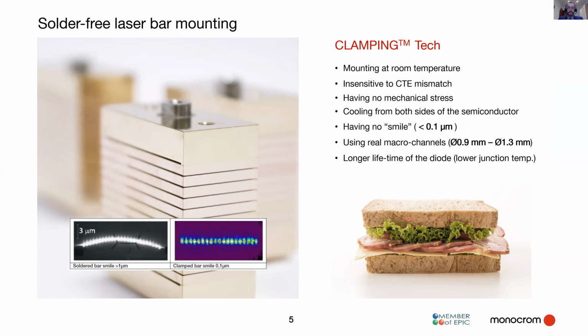Our mounting technology for laser bars is somewhat different compared to what's common on the market. At Monocrom, we make sandwich structures comprising 2 electrodes, which is shown on the lower right section of the slide. In between the electrodes lies the semiconductor. We clamp this structure, and while applying a force, we ensure good mechanical and electrical connection to the laser bar. And we avoid using solder material. This allows us to mount our sandwich structures under room temperature conditions.